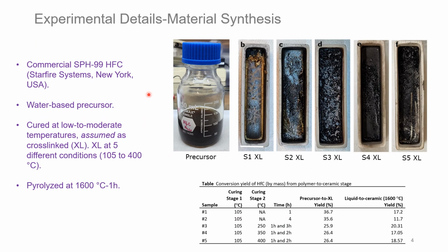In this work, a commercially available single-source and liquid-phase hafnium carbide precursor was utilized to manufacture hafnium carbide powders. Various cross-linking temperatures were studied to determine the low-temperature curing conditions for the precursors, followed by pyrolysis at 1600 degrees centigrade for 1 hour in an argon environment. The curing conditions that are shown here were determined by our industry partners. The precursor was thermally cross-linked at these 5 different conditions, and the figure shows these 5 different samples. They were cured at 5 different stages.